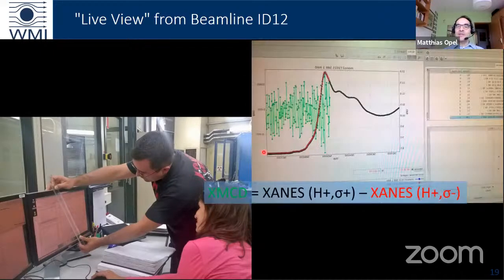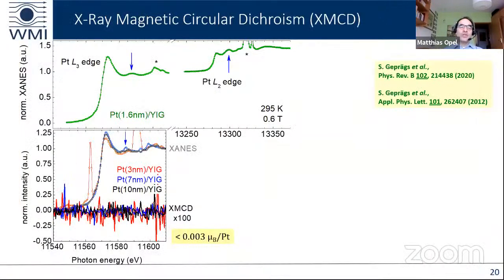And this was a screenshot at that time. So this is the X-ray absorption. And what you see in green is now the difference spectrum of two different X-ray absorptions, one with positive and one with negative helicity. And this difference spectrum is the XMCD, the X-ray magnetic circular dichroism. I now want to show you the XMCD signal. This is shown here for these three samples.